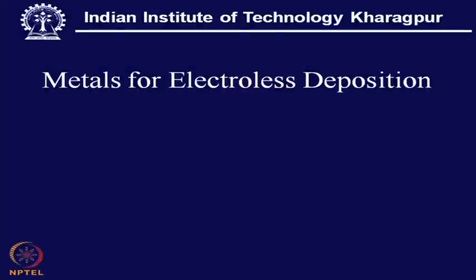Now, metals for electroless deposition, we have all the metals: nickel, chromium, cobalt, we can also have silver, copper, gold, everything is possible. But what is advantageous, along with nickel we have a little bit of phosphorus also coming from this hypophosphite, and that nickel phosphide, with a small percentage of phosphorus, adds to the hardness. Similarly, if we have